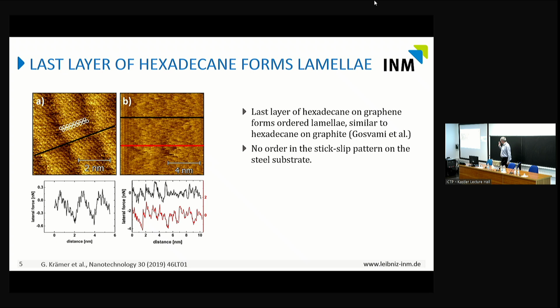And then if you actually look into high-resolution images, friction force microscopy, you see that there are these stripes, and within the stripes you see little atomic structure, and I have sort of suggested here in white rings the structure of the alkane lying in these lamellae. And this has been confirmed before in many experiments on flat surfaces like graphite or so by STM, also in hexadecane. And what happens is essentially alkanes fit surprisingly well to graphene structurally. So they like to order and form ordered layers with a little superstructure here, and we get regular stick slip on these lamellae, on the alkane layers, and then we get this low friction, while we get this very irregular and large stick slip on the steel surfaces.